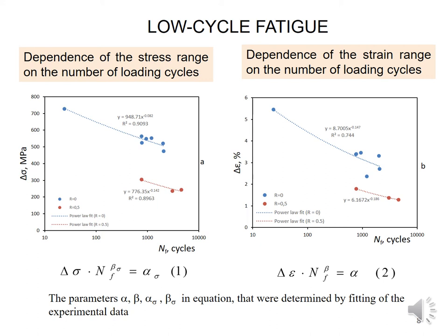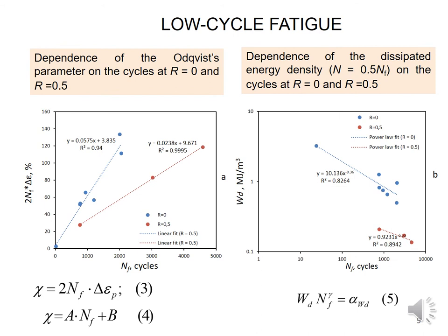A similar effect of stress ratio on fatigue lifetime was observed while using stress-strain range as a failure criterion. The strain amplitude and number of cycles to failure under low cycle fatigue are described by the empirical relationship Formula 2. The fatigue lifetime was also estimated using the Odqvist parameter, which characterizes the accumulated plastic strain and under uniaxial cyclic loading is determined by Formula 3. According to the left figure, the Odqvist parameter is linearly proportional to the number of loading cycles before failure and well described by dependence 4.